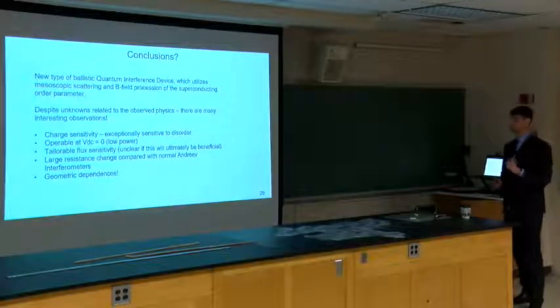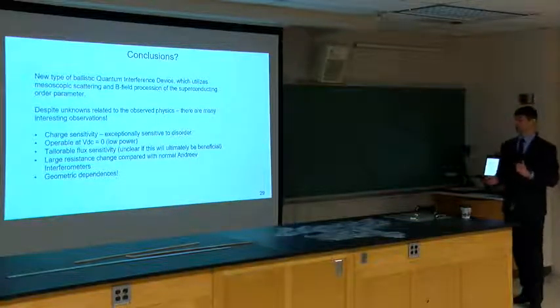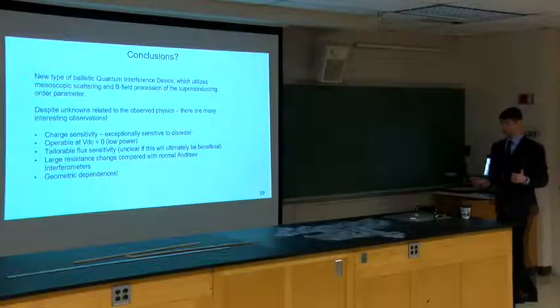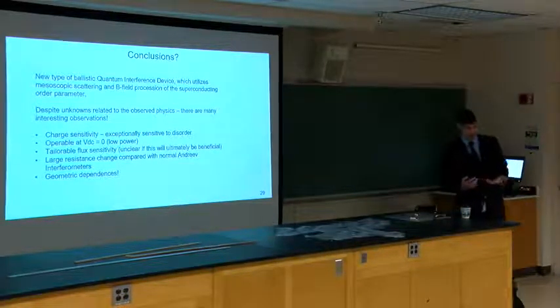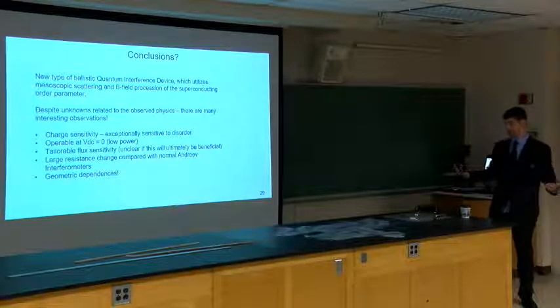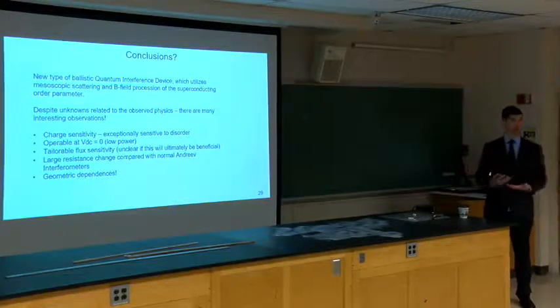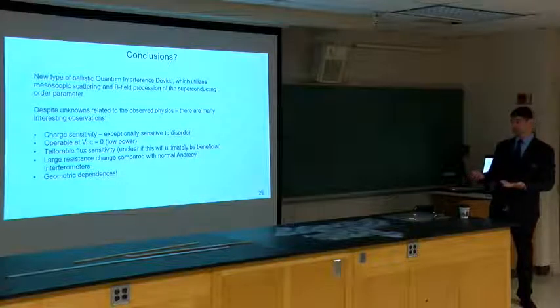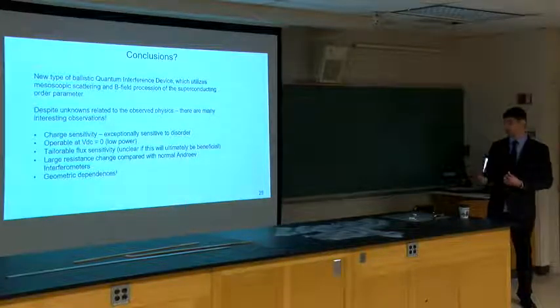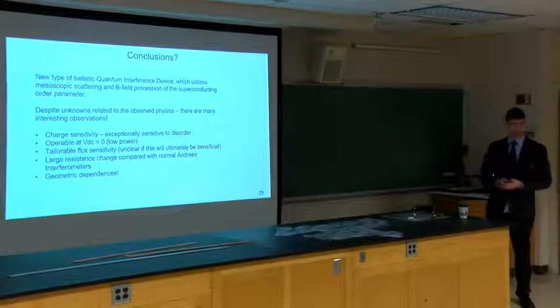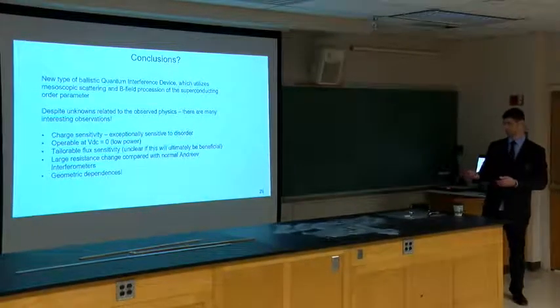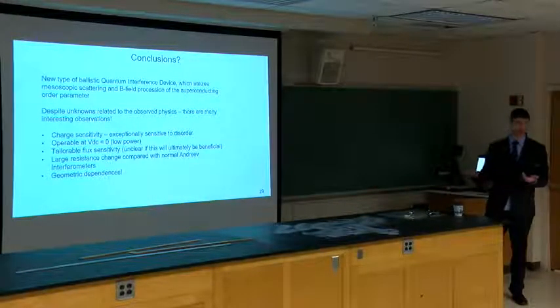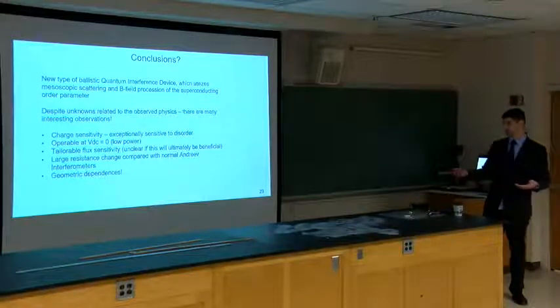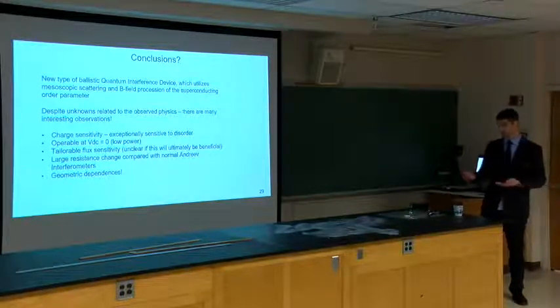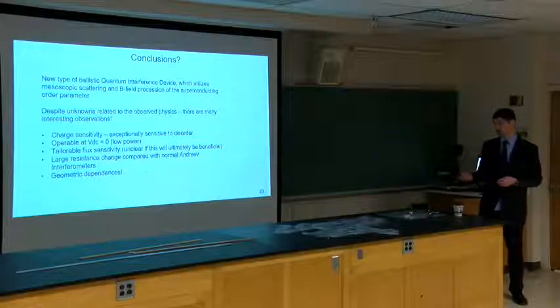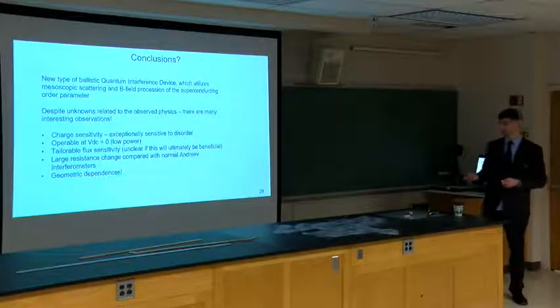there's a lot of very big positives that come from this. So firstly, the charge sensitivity. While it's not clear if having a charge interferometer would be useful, this system itself is exceptionally sensitive. 5 times 10 to the 8 is amazingly sensitive. It's operable at 0 volts, so it should ideally be low power. You can tailor the flux sensitivity. It actually has a large resistance change compared to the previous Andreev interferometers.